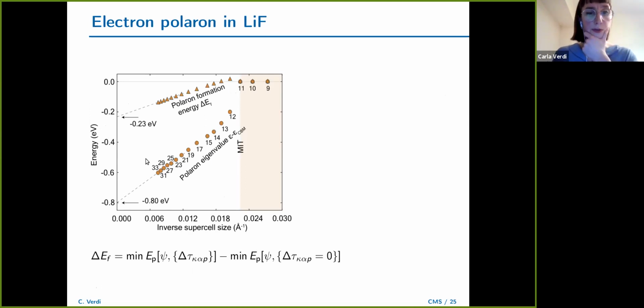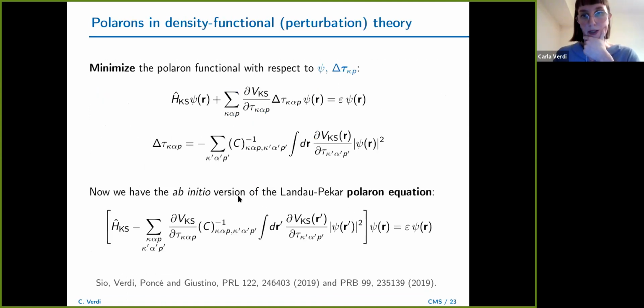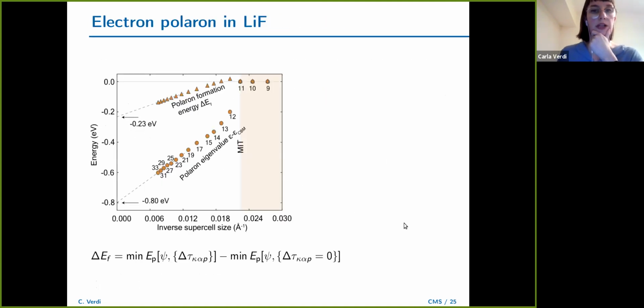So first of all, we can calculate the energetics of the polaron. So the energetics of the polaron is given basically by this polaron eigenvalue here, epsilon. But this is not actually the total energy of the polaron. The total energy of the polaron should also include a contribution of lattice strain. This is normally defined also in normal DFT calculations as the minimum of the total energy where you have the added electron and the atoms are displaced, minus the minimum of the energy when you have the added electron, but the atoms are not displaced, okay?